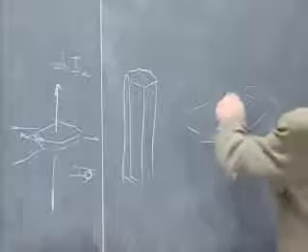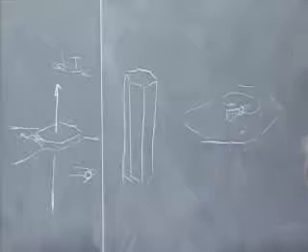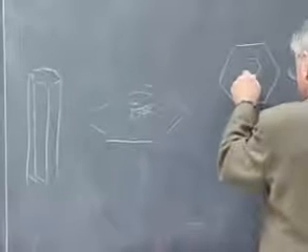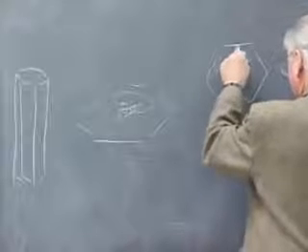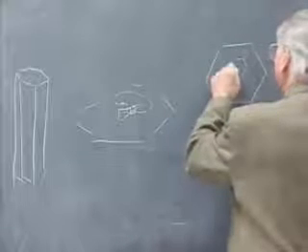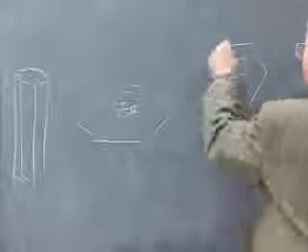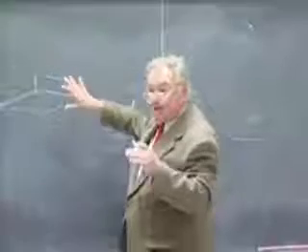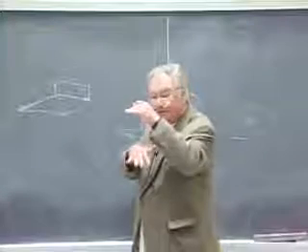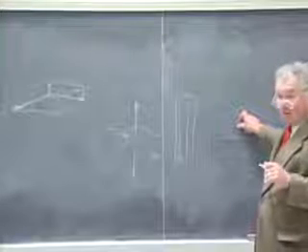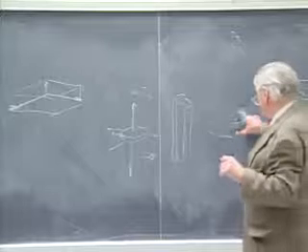And this is the so-called screw dislocation mechanism for crystal growth. And after the crystal has grown for a while, you can see spiral steps on the surface of the crystal that correspond to this dislocation winding around. Okay, so why should crystals grow most rapidly along the direction of the shortest translation? It's going to be a lot easier to create a screw dislocation with a Burgers vector for a translation that is short rather than the translation that's 10 or 20 angstroms.